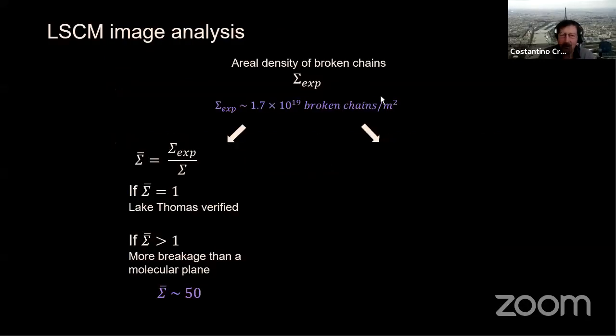So we can normalize our data. This is what we measure experimentally, and we can normalize that by the Lake Thomas prediction for the same network. We define this sigma bar, and that sigma bar can be one if Lake Thomas is verified, or can be much larger than one if you break much more than a molecular plane. Typically, in the example I showed you before, if we take this number of broken chains, it's about 50 times the monolayer that you would predict from Lake and Thomas. Of course, this sample was broken far from threshold condition. There was viscoelasticity, so it's not really very surprising.